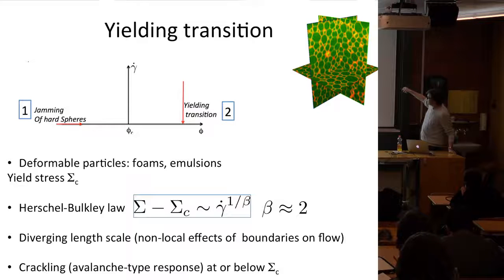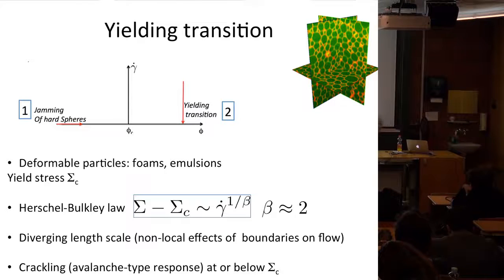It seems that this approach is again a phase transition, and it appears in several observables. So one that you can look at is the stress-strain rate relationship. And you see that the flow curve is singular when sigma goes to sigma c. So the relationship between strain rate and sigma, where sigma is the stress, so that's how much you increase the stress on the system. That's how fast you flow. There seems to be a singular relationship between those two.